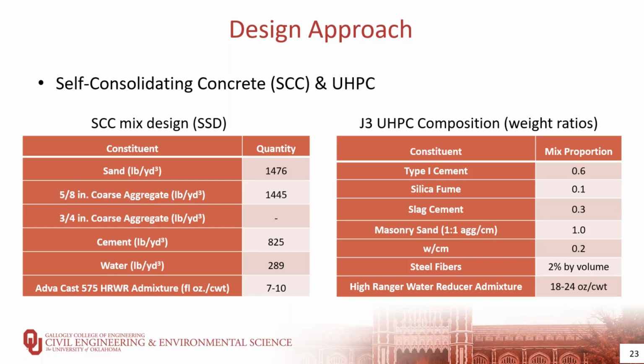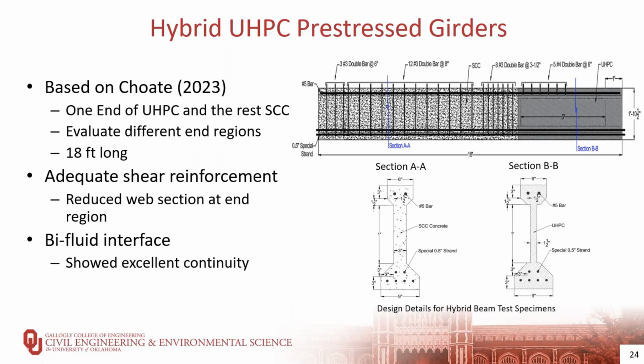A high-range water-reducing admixture was added to achieve the desired slump flow that we need for our SCC mix, and the targeted slump flow for all the specimens was between 25 and 27 inches.